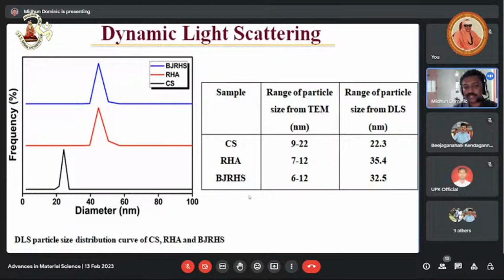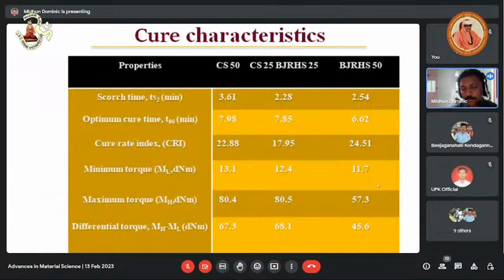And dynamic light scattering is also conducted to determine the particle size distribution. For commercial silica the particle size is around 22, rice husk ash 35, and BJRHS 32 nanometers. So all the prepared particles are in the nano regime. We could obtain BJRHS rice silica with excellent purity and excellent surface area with lower particle size. So actually we thought, oh eureka, we have found a good material for replacing commercial silica in green tire formulation.